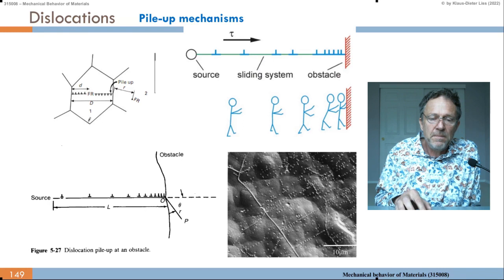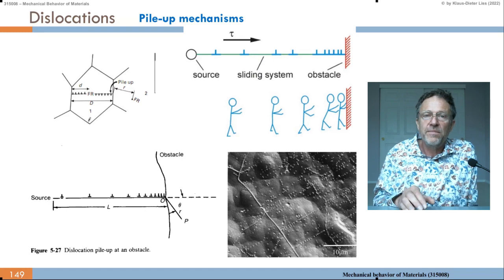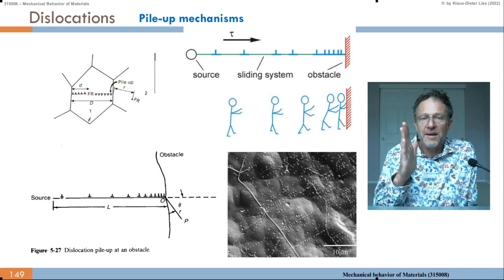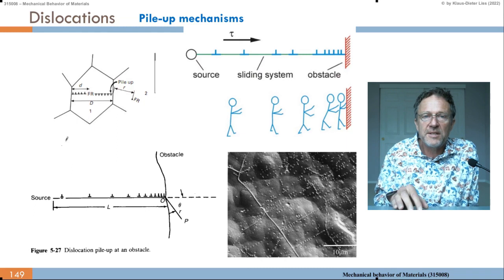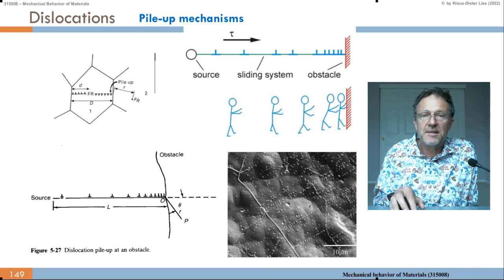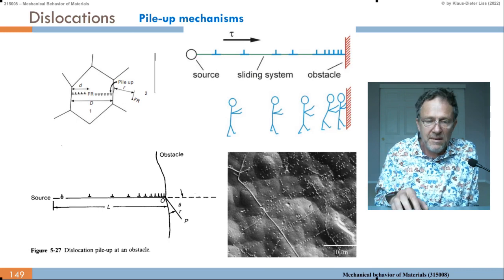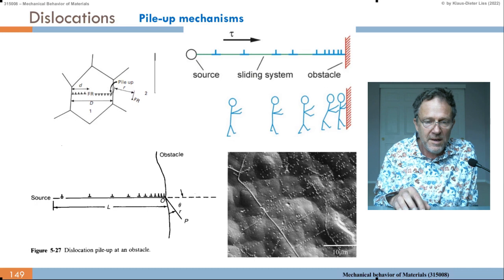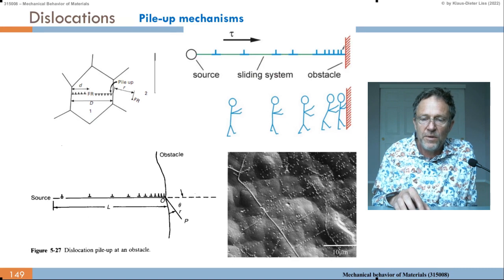It lines up behind the first dislocation, either 90 degrees or 45 degrees, depending on the sign of the dislocation. So they attract each other and they line up in lines. We have seen that, these dislocation walls. We studied that maybe two lessons ago. And how far can it move? Well, until it comes close to the first dislocation.